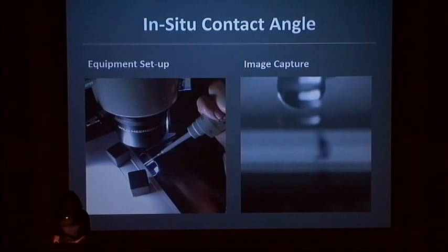Not every conservator, then, has FTIR to identify the papers, but the contact angle test might suffice in assessing the paper's surface polarity and therefore potential adhesives suitable for use. In this test, we used a small mechanic's mirror set at a 45-degree angle with a few microscope slides to raise the paper so it could easily be viewed in the reflected image with a microscope. The paper being tested was weighted down and a 100 microliter drop was placed on the paper. We waited for 3 seconds and captured the image.